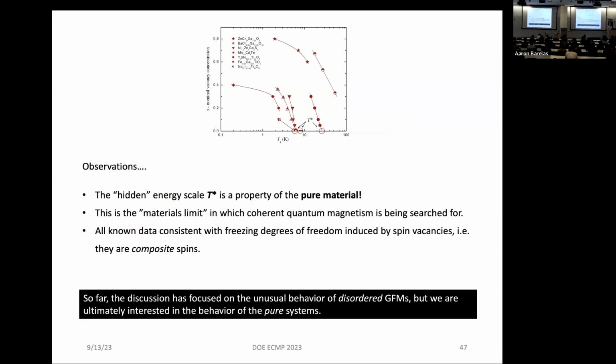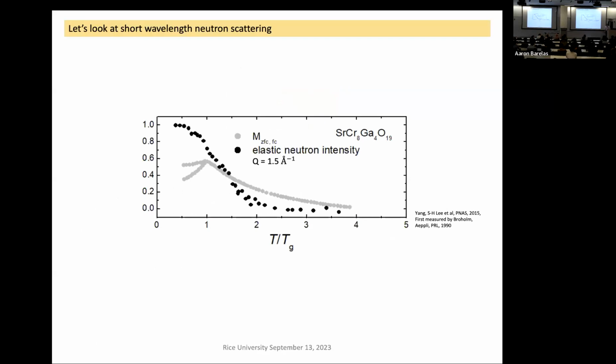Okay, so we're interested in behavior of pure systems, and you might be surprised that people have done a lot of measurements on the pure systems. One of them is neutron scattering. You might say, well, what are the things doing at this energy, at this temperature? Here I plot on a reduced scale the susceptibility for strontium chromium gallium oxide, the kagome system, and the elastic neutron intensity at a short wavelength. So there's no long-range order, no Bragg peak, but there's a broad background that characterizes the magnetic short-range order and follows this temperature dependence. Just the fact that you can see this in neutrons means that it's probably due to the bulk of the spins. So that's strontium chromium gallium oxide.